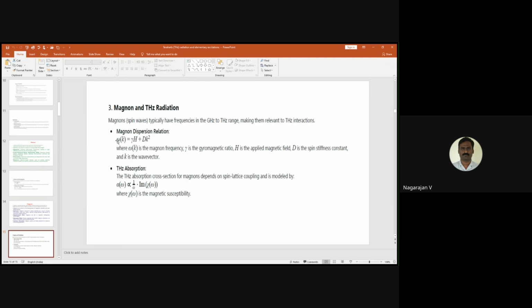Dispersion relation: omega k equals gamma times H plus D k square, where omega k is the magnon frequency, gamma is the gyromagnetic ratio, H is the applied magnetic field, D is the spin stiffness constant, and k is the wave vector. So this is the dispersion relation, and the terahertz absorption alpha omega. This terahertz absorption cross section for magnons depends on spin lattice coupling and is modeled by this one, where chi omega is the magnetic susceptibility.